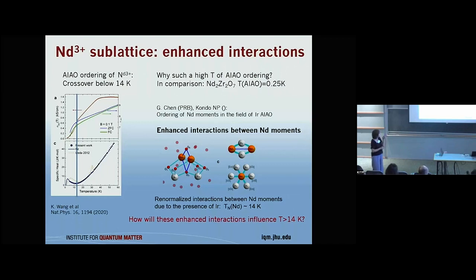So 14 Kelvin is for this particular sample. If you look at literature, it varies a little bit, because in non-stoichiometric samples it actually gets a little lower. The highest temperature I've seen in literature was 15, but there are some lower temperatures. There is specific heat compared here from Moiré. Our sample has 0.02 off stoichiometry. So for the completely stoichiometric sample, it also shifts a little bit higher.